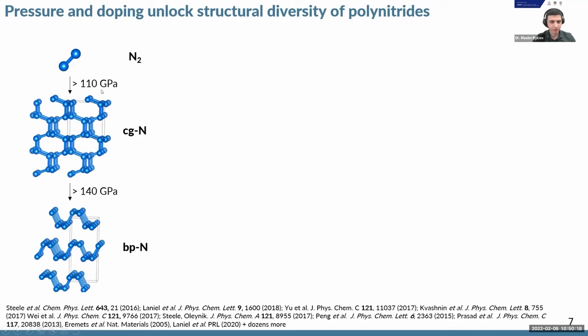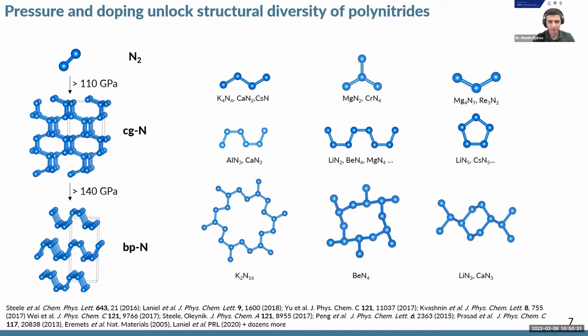So due to the very high polymerization pressure, these compounds are not really useful for applications as high energy density materials. However, if we add an additional element, usually an electropositive metal, we can stabilize various polymeric nitrogen species, starting from really small chains to a few membered chains to rings and 2D and 3D extended networks. So these materials were mainly addressed theoretically in the past years. And when we started this research, only a few experimental studies on pentazolate were published.